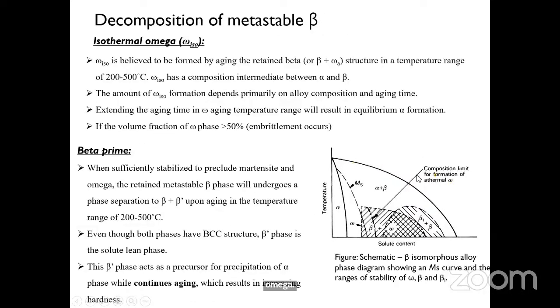fraction. Suppose you are heating this metastable beta alloy in this temperature range, for example 300 to 350 degrees centigrade, and you are holding for sufficient time, then this isothermal omega starts precipitating out in this region. That means if you are keeping for more than 24 hours at this temperature, 200 to 500 degrees, then omega starts precipitating out. Then it is called isothermal omega. This isothermal omega has composition intermediate between alpha and beta, and when you keep on increasing the aging time, this omega will act as a precursor for the formation of alpha phase.